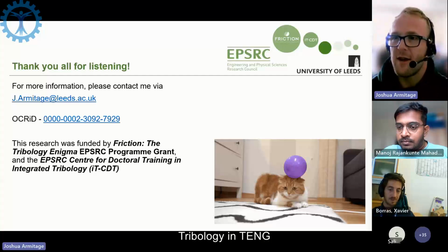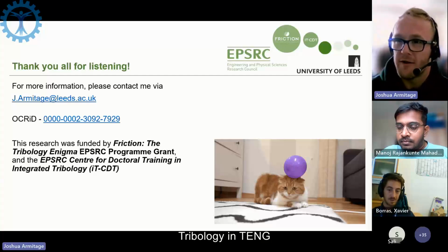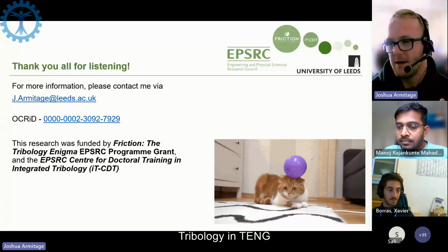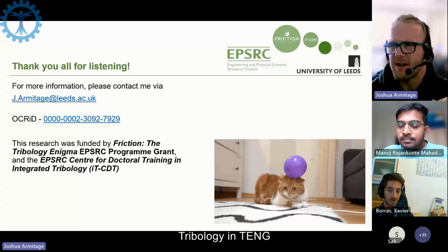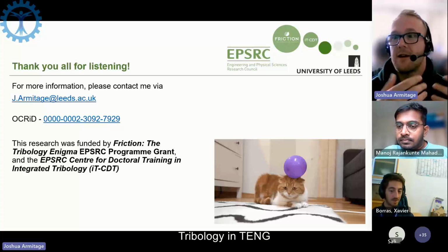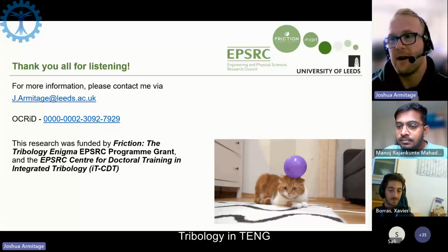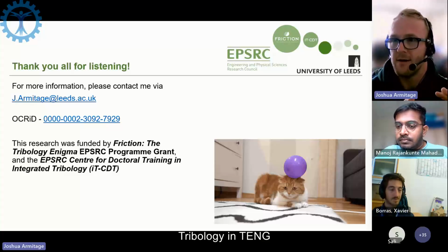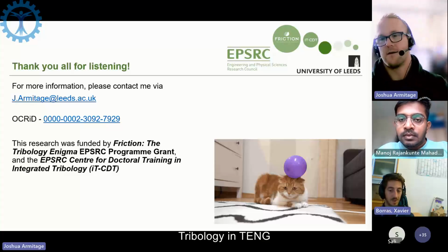But in terms of piezo technology, the moment you remove the strain, the charge is no longer there because you don't have that disparity in electron cloud throughout the material. Hopefully that explains it a little better, but piezo technology can be used in conjunction with triboelectric technology as well. There's no reason for them to be competing. They can be used in addition to each other. Sure.